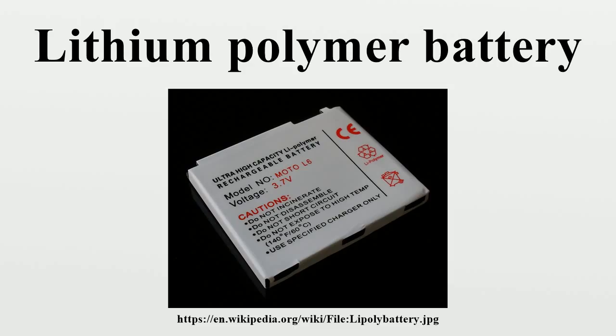Other terms used in the literature for this system include hybrid polymer electrolyte, where hybrid denotes the combination of the polymer matrix, the liquid solvent and the salt. It was a system like this that Bellcore used to develop an early lithium polymer cell in 1996, which was called plastic lithium-ion cell, and subsequently commercialized in 1999. A solid polymer electrolyte may be, for example, a compound of lithium bisamide and high molecular weight poly(ethylene oxide). The performance of these proposed electrolytes is usually measured in a half-cell configuration against an electrode of metallic lithium, making the system a lithium metal cell, but it has also been tested with a common lithium-ion cathode material such as lithium iron phosphate.